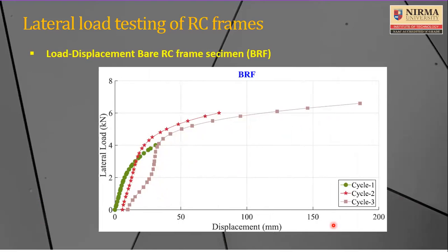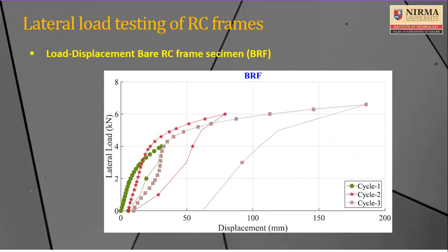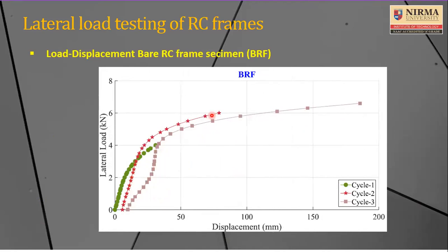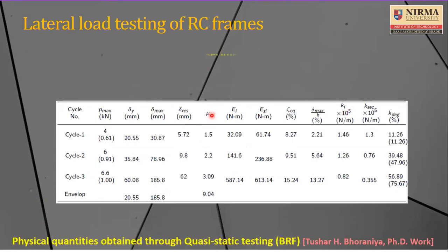Of course, it is monotonic half cycle loading, so it does not go to the other side. And because we do not have a very well controlled backward unloading path, we have removed that unloading part, and we rely on the forward path of the loading. And then we have calculated all the important parameters like maximum load, the yield displacement, maximum displacement, residual displacement, the displacement ductility cycle by cycle and envelope by envelope, as well as the elastic energy, the strain energy because of the energy dissipation, and then the equivalent damping ratio, and then drift ratio, and then the initial stiffness and the second stiffness to calculate the stiffness degradation.